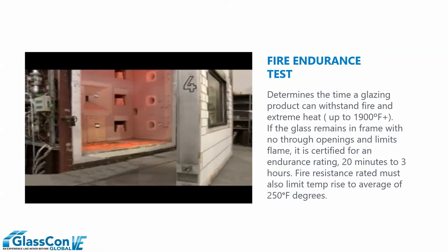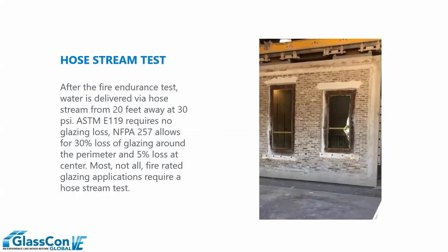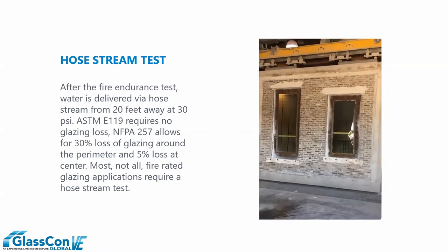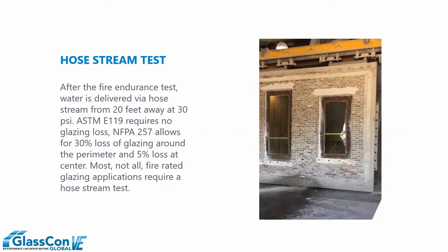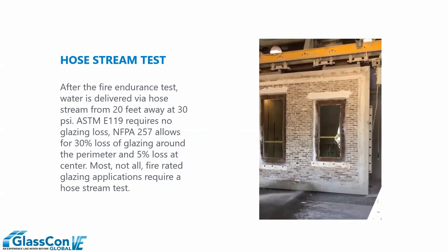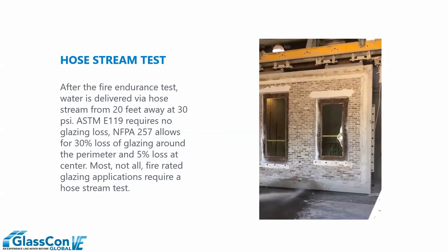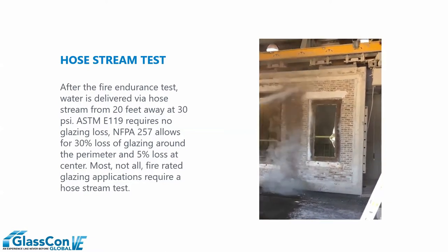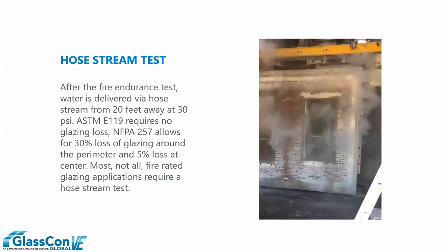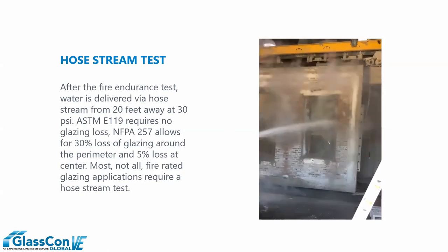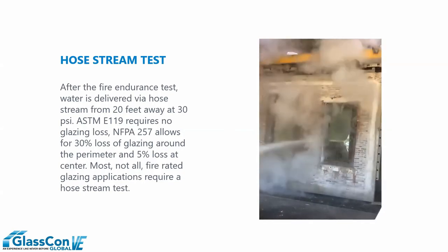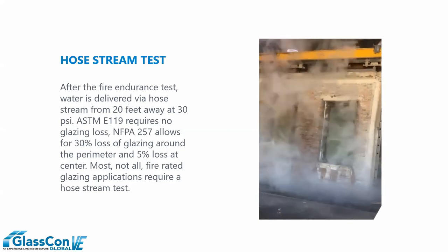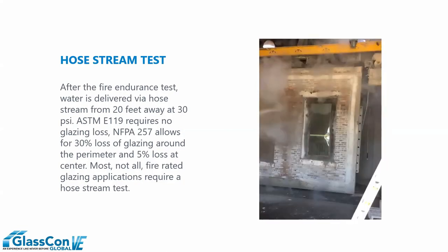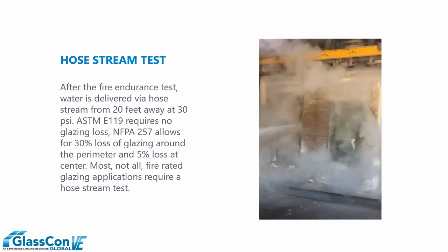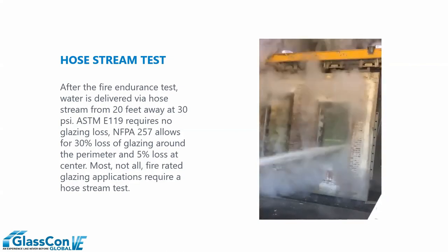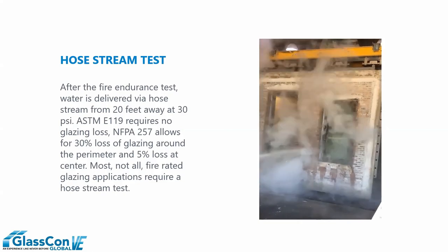This leads us to our next test standard, the hose stream test. So now we have the test specimen at the surface of the glass and frame that had been exposed to extreme temperatures, 1700, 1800 degrees Fahrenheit, now facing the center of the test facility, where we have a fire hose waiting at a predetermined distance, 20 feet, and a predetermined pressure, 30 psi. Water is evenly distributed across the surface of the glass and framing. The time period of this test is determined by the size of the test specimen and the amount of clear view. There is allowable breakage, 30% at the perimeter, 5% center of glass. However, the glass is not allowed to leave the opening.